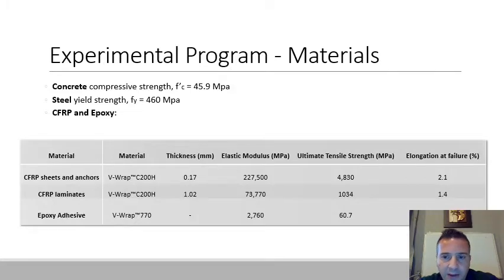Here it is. So basically these are the material properties. These are CFRP sheets and anchors. They are V-Wrap C200H. The thickness of the sheet is very small, 0.17 millimeter. Their elastic modulus is very close to steel. Tensile strength is 4,830 megapascal, and the elongation at failure is around 2%.